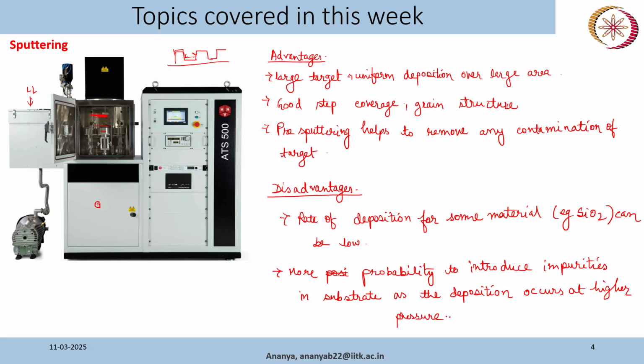Okay. Now, what process you will actually use, what kind of deposition technique, whether evaporation or sputtering, depends on what you are aiming for. Say, if you want a good step coverage, then you will go for sputtering. If you want to go for larger area, then you will go for sputtering. If you want to deposit your metal and you want a directional deposition, then you go for evaporation.